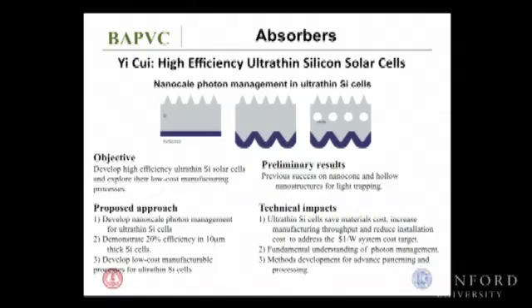Try to look at very thin silicon solar cells. We are not talking about 100 micron anymore. We are talking about 10 microns or even thinner. Can you come up with the right structure when the light comes in, having the right nanoscale photon management, whether it's a cone-shaped structure or a hollow structure engineered in the silicon, to trap the sunlight inside? Eventually, only 10 micron or less can absorb all the above bandgap photons, and demonstrate a decent efficiency as high as, let's say, 20%. This will help reduce the silicon solar cell cost by quite a bit.